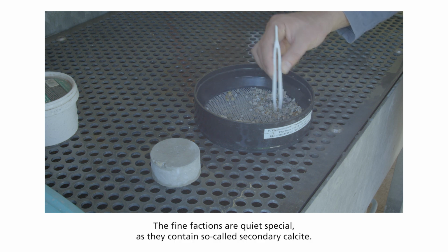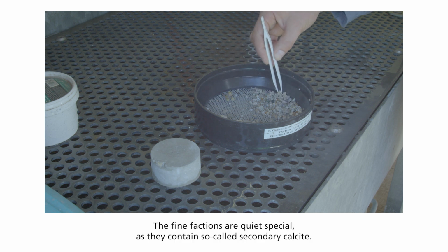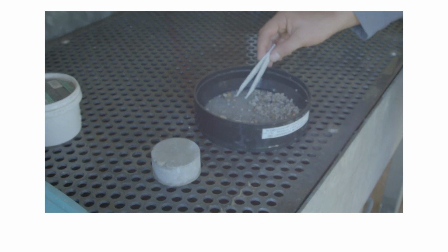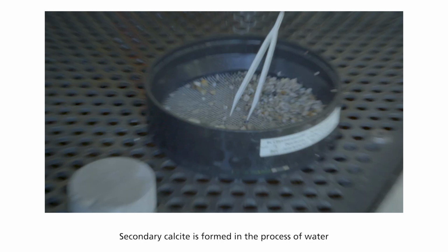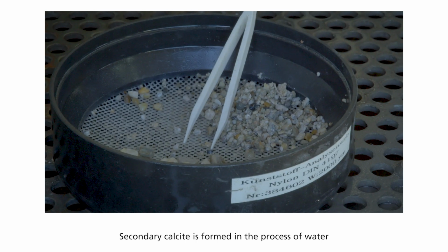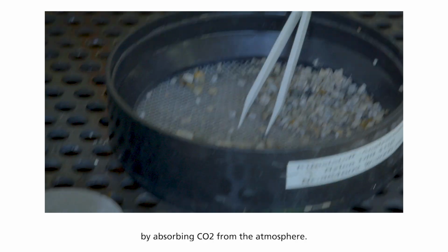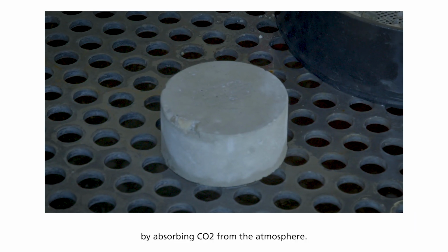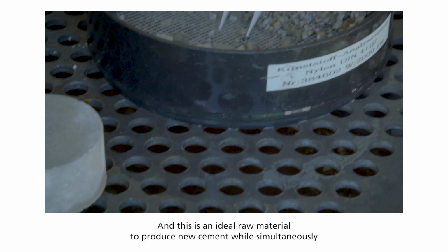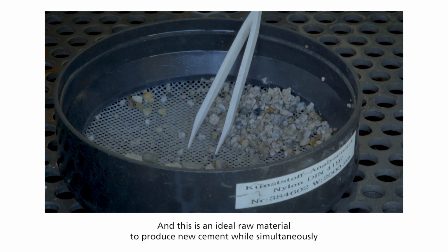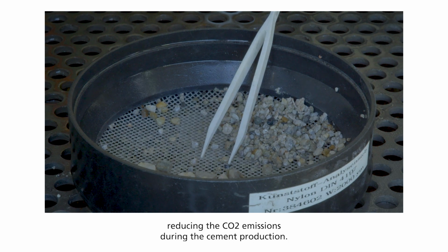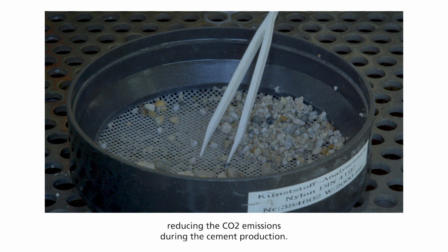The fine fractions are quite special, as they contain so-called secondary calcite. Secondary calcite is formed in the process of weathering by absorbing CO2 from the atmosphere. And this is an ideal raw material to produce new cement while simultaneously reducing the CO2 emissions during the cement production.